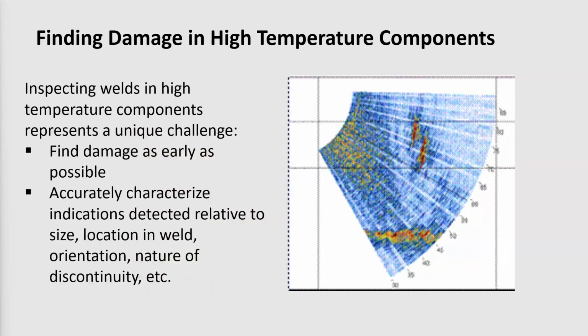Now, in terms of the inspection, as most of you are aware, there are a number of tools out there that are commonly used for the inspection of the steam line piping. One of these is ultrasonic testing, and any of the various versions of ultrasonic testing that are available now for these inspections. What you're trying to do, as with any use of the non-destructive inspection techniques, is to find the damage as early as possible, and then when you do find indications, to accurately characterize those indications. It's important to understand that when you're looking at these welds, simply the fact you find an indication doesn't mean that indication represents advanced creep damage.